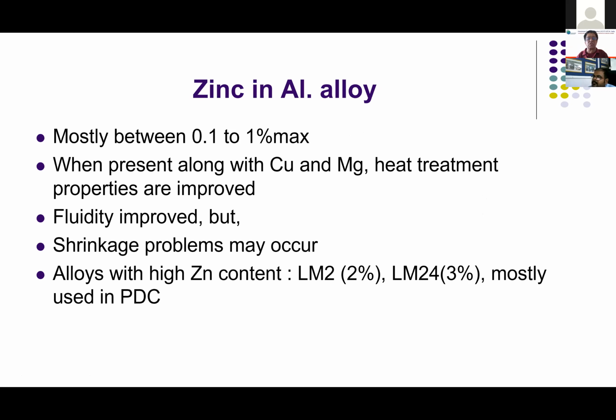When present along with copper and magnesium, it adds greatly to improve the properties. For example, if the magnesium is in the border range of 0.3, 0.35, presence of zinc helps you to improve the hardness. So therefore, zinc to some extent improves the heat treatment properties. Fluidity improves, but zinc also has got a negative problem. Shrinkage problem may occur. Microporosity, macro shrinkage may occur. LM24, okay, mostly used in PDC.